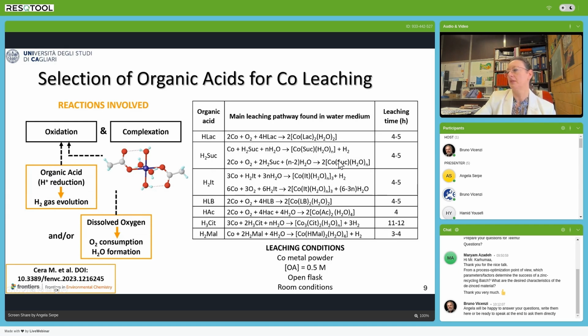In the case where we observe the formation of hydrogen as product, it means that the organic acid is playing the role of oxidant in the reaction. The reactions that don't provide hydrogen as product are instead going ahead through oxygen consumption. So oxygen dissolved in the mixture is able to oxidize the metal and make it available for coordination. So as you can see in this table, not all the organic acids behave in the same way.